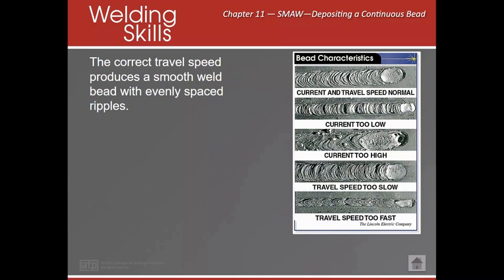Your current being too high, so that's your amperage being too high, that's where you're going to get a lot of undercut into your weld material, like this little area right here. You're going to get some excess spatter. And your travel speed too slow is going to make a weld too big. One of the downfalls of that is, if you're welding on a thin piece of material, then you're putting too much heat into that material. So you're going to have a chance of blow through. You're going to start to distort that material.